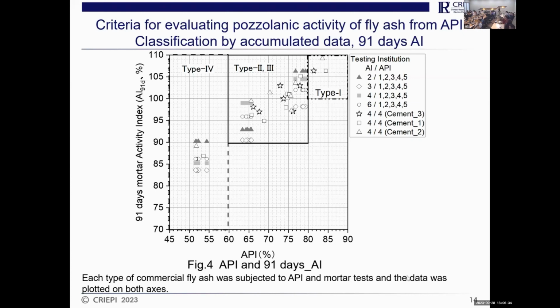In mortar activity, for type 1, the lower limitation was 100%, and for type 2 and type 3, the lower limitation is 90%, and type 4 shows the lower limitation as 70%. And to see the horizontal axis, we determine for type 1 the lower limit is 80%, and for type 2 and type 3, the lower limit is 60%, and for type 4, the lower limitation is 40%.